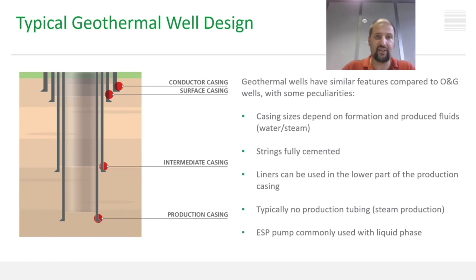Production casing with sizes as big as 9 5/8 and 13 3/8 inches is a common design. Strings are fully cemented up to surface, even liners and tiebacks, to reduce the risk of annular pressure buildup and buckling under compression loads. Cement not only displaces the drilling mud, which is a source of APB, but also supports the string, reducing the lateral deformation of the string during buckling. A proper cement job is a key success factor for geothermal applications.